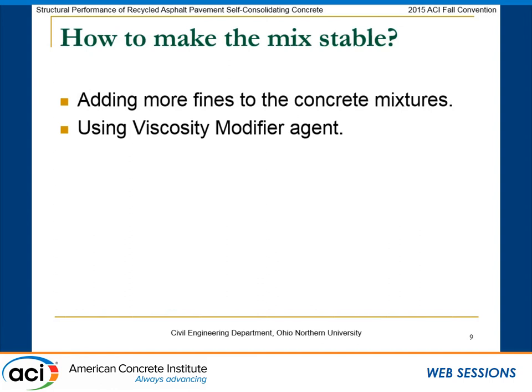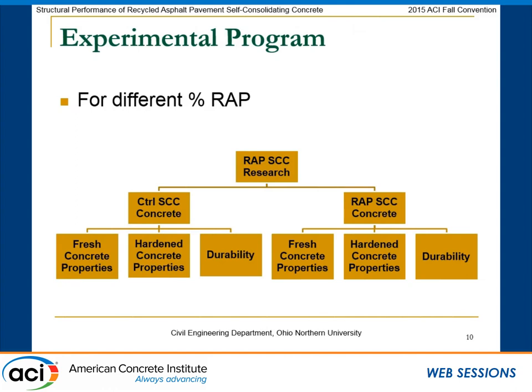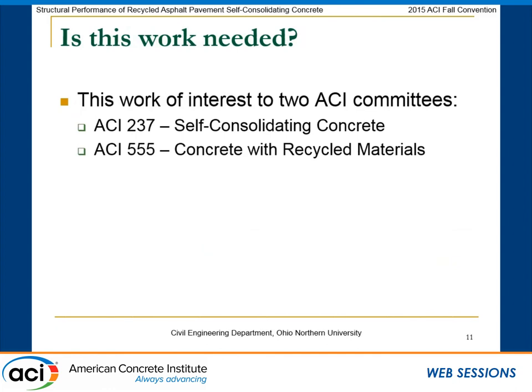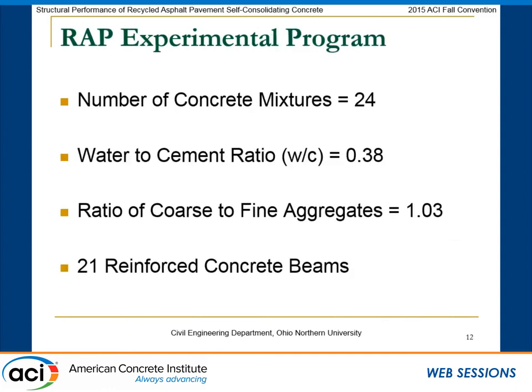And for SCC design, you want to make sure that your mix is stable because it's a high flowable concrete. So you can do that by using fines or using VMA. So we decided to use the VMA for this research. So this is a research program. So basically, we looked at the fresh and hardened concrete properties, and also we looked at the durability of the concrete for the control mix and for those with RAP. So this research program will be of importance to this committee, ACI 555, and also for ACI 237, which is the SCC committee.